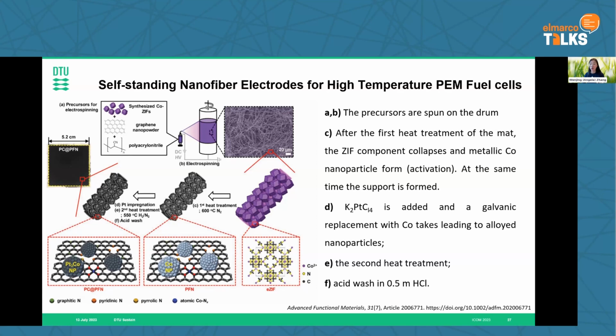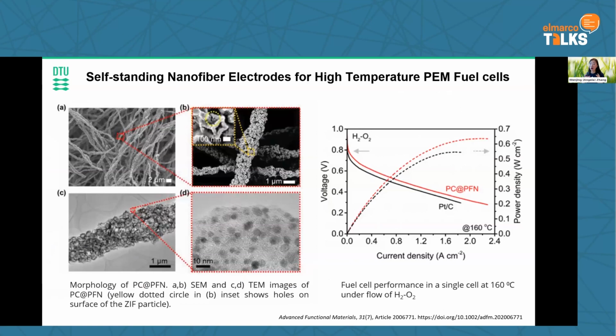So we created this platinum cobalt catalyst. And those electrodes are very, very flexible. So you can see those pore structures and those electrodes that are carbonized as well. And then they can conduct the electrons, and the catalyst can trigger the reaction. And by those, we can produce the electrode by roll-to-roll production, cut into pieces, and then hot press on the membrane. So we can make the MEA in a much more convenient way as compared to industrial practice.